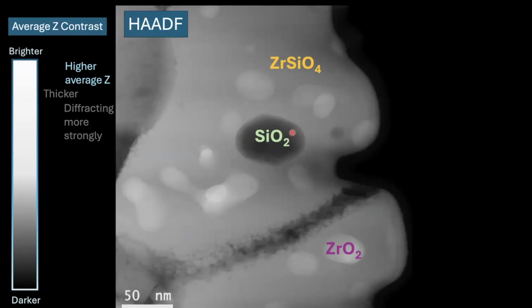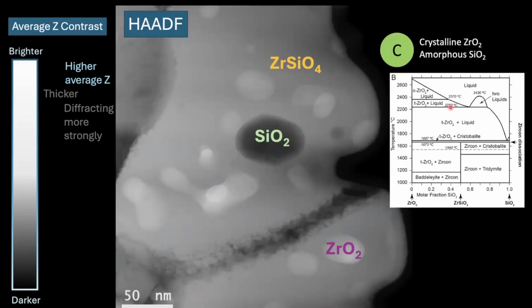The darker stuff in HAADF images is silica, and the brighter stuff is zirconia. I still need to identify what specific mineral the silica or the zirconia is. That's a work in progress right now. But we have crystalline zirconia and amorphous silica. So again, this can make sense. It's a high temperature thing.